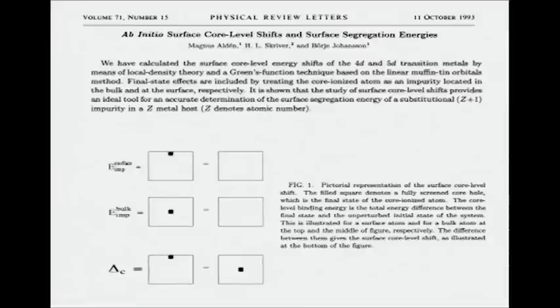Okay, this is actually also a nice follow-up to something that Niels was talking about, because the basic idea of this paper, which is 13 years later than the 1980 paper, is following up something that Niels picked out in the text of the original manuscript. It's looking at the so-called surface core level shift, that is, the difference in the photoelectron binding energy for an atom in the bulk of its own solid and at the surface of its own solid.